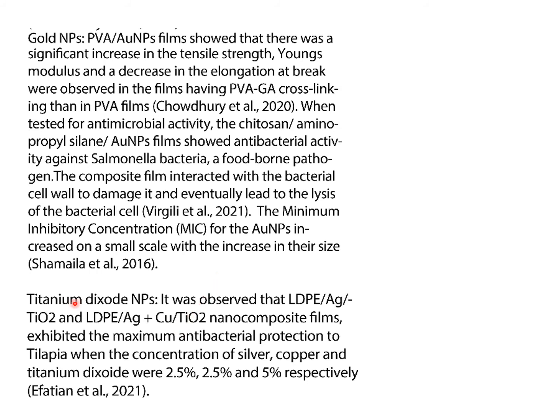With respect to titanium dioxide nanoparticles, it was observed that LDPE films with silver and titanium dioxide, and LDPE films with silver, copper and titanium dioxide nanocomposite films exhibited the maximum antibacterial protection to tilapia, which is a fish, when the concentrations of silver, copper and titanium dioxide nanoparticles were 2.5, 2.5 and 5% respectively.